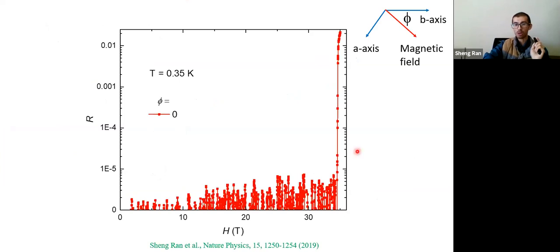So here, I showed you this data. I'm just plotting it on a logarithmic scale. So resistance as a function of field. It was 0 up to 35 Tesla. Then there's a five-order-of-magnitude jump. Here, this is when we apply the magnetic field along the b-axis.